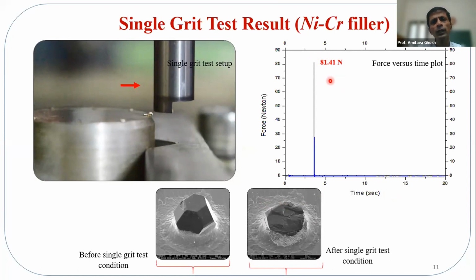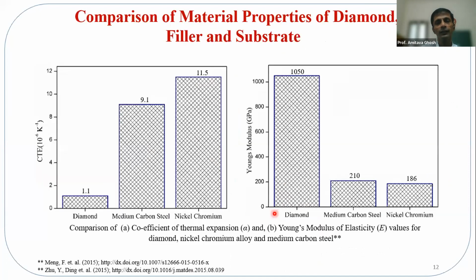The impact is much more, even the failure takes place at a much lower load. So what happens? This particular grain basically fails, and that fails not abruptly. It is always tending to fail at the bond level. The breakage takes place at the bond level because the residual stress is there. If you see the coefficient of thermal expansion between the diamond and the medium carbon steel, that is the substrate, there's a wide gap. And of course, the Young modulus also, there is a wide gap. So as a result, what happens when it cools, the residual stress is extreme.